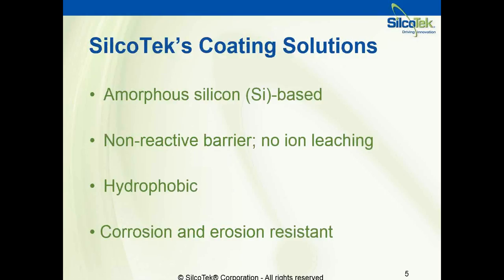So all of SilcoTek's coating solutions are amorphous silicon based, so they're a very non-reactive barrier. They prevent ions from leaching out of the substrate by actually creating a physical barrier between the process and the substrate without obstructing the manufacturing process whatsoever. Being silicon, they're very hydrophobic relative to an uncoated bare stainless steel substrate, for example, and they resist corrosion and erosion very well, which will prevent particulate from building up and contaminating the process stream.